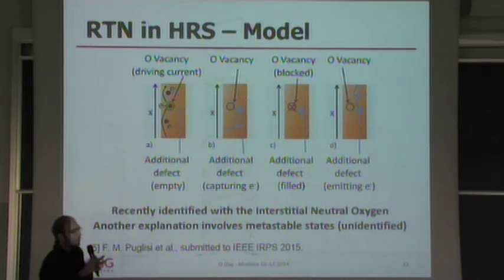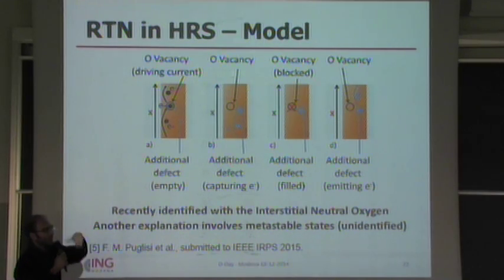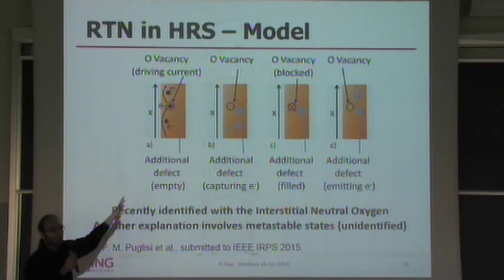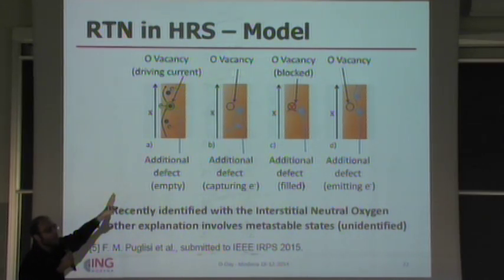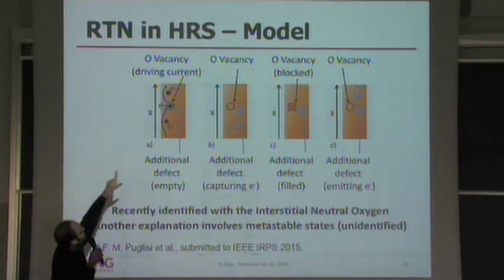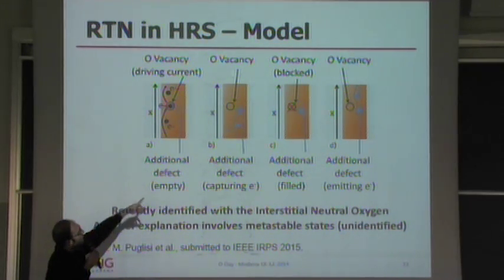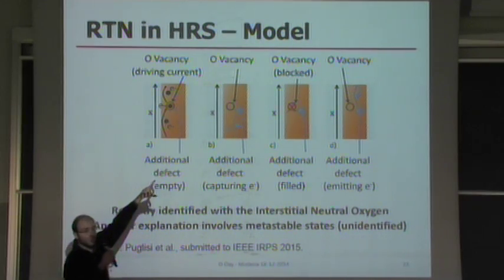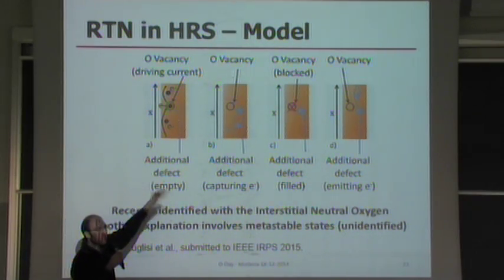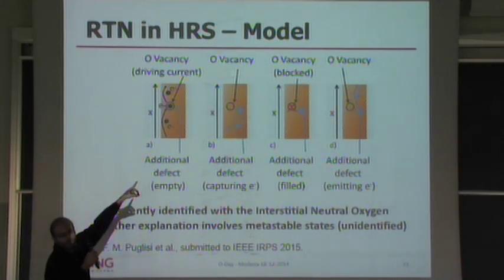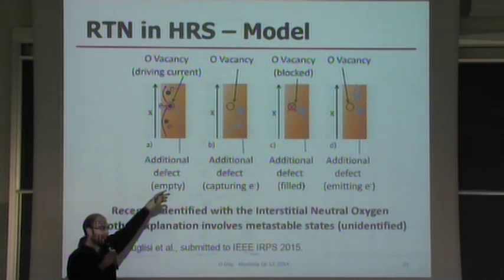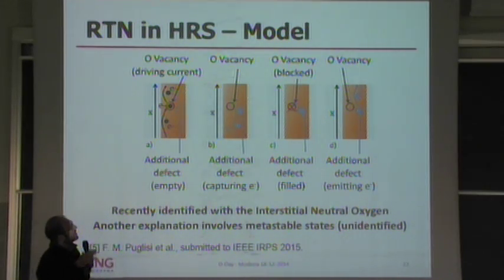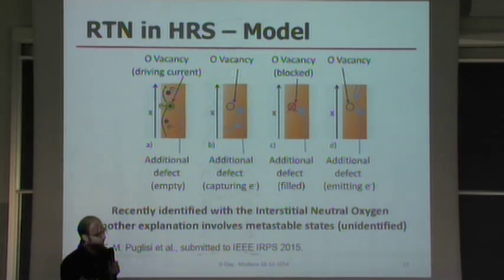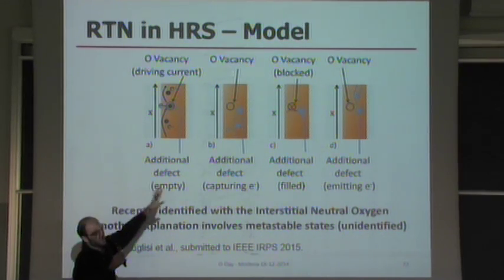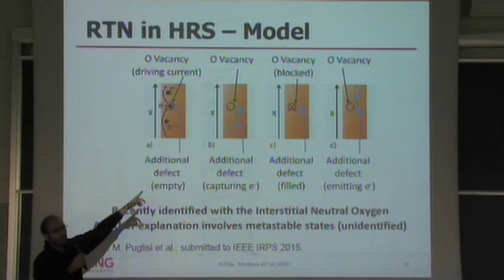And we ended up proposing a model for how these defects can get activated and deactivated. We suggested that there may be an additional defect, we don't know which kind of defect this is, that is initially empty and everything flows smoothly. This oxygen vacancy is carrying some current. But upon a charge capture by this defect, the local electric field induced by the trapped charge can modify the field of the oxygen vacancy in such a way that the oxygen vacancy is not available anymore for charge transport. However, the initial situation is restored upon the defect's charge emission.